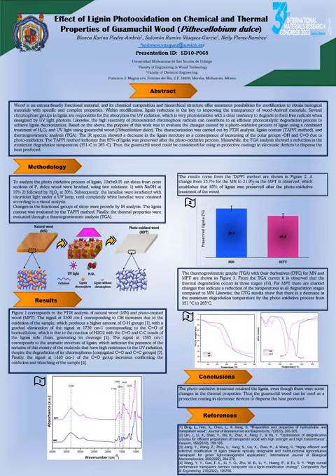Within the methodology, the changes in the functional groups of Guamachil Wood were determined by infrared analysis. The lignin content was determined by the TAPPI method, and finally the thermal properties were evaluated by thermogravimetric analysis.